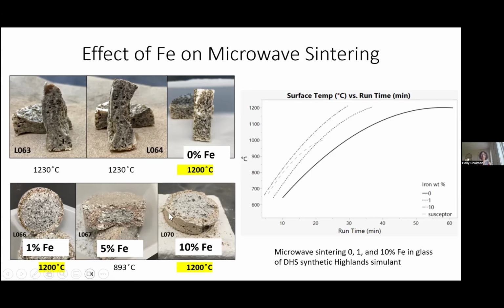So what's happening here is because these runs are so quick, with the 1% not quite as quick as the 10%, there's something called heat work. The whole question about temperature is very confusing when it comes to microwave. We are always assuming some sort of uniformity of temperature, and that you're really measuring either the surface with a pyrometer or something nearby the surface with a thermocouple. And what's happening in the microwave situation is that you're directly heating internally. And so your surface temperature that we're measuring here is not quite correct. And it might even be true that it's just as hot on the inside.